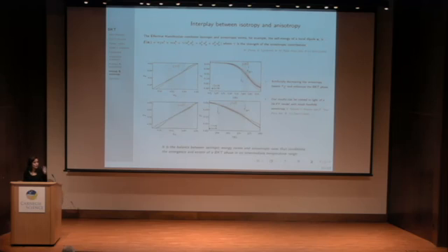I just took one energy term, which is the self-energy of the dipole moments, and I looked at the anisotropic contribution in this term only, and I switched it off. So I didn't erase the anisotropy, I just artificially made it a little bit less strong. This resulted in a drop of TC, meaning that the ferroelectricity became less robust, and also resulted in an extension of the BKT phase.